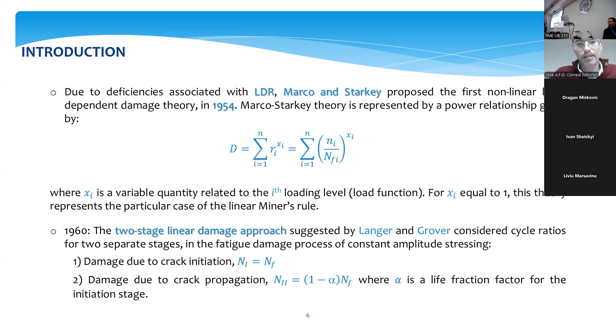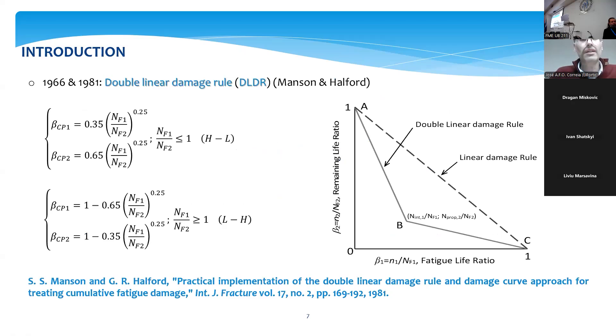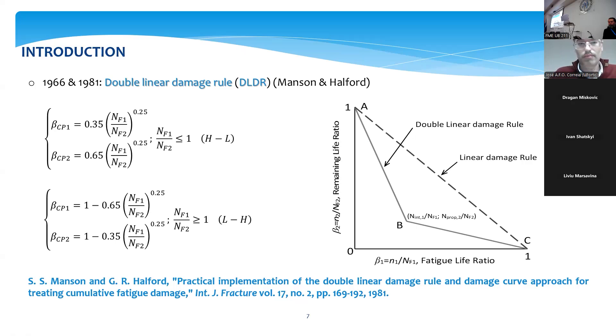After that, a two-stage linear damage approach was suggested by Langer and Grover, considering cycle ratios for two superimposed variable stages — one related with fatigue crack initiation and another with fatigue crack propagation. In the 1980s, a double linear damage rule proposed by Manson and Halford was introduced. This is interesting because we can consider different sequences like high-low or low-high, and we can identify from this law the knee of the model.